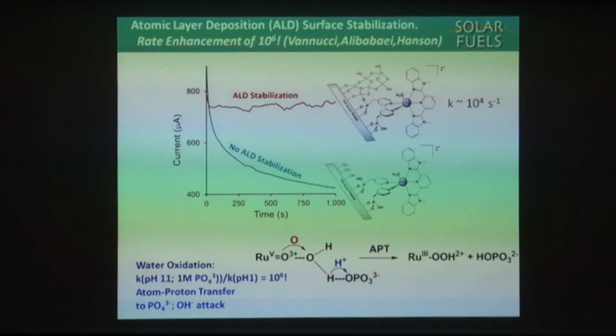With this one, we first bound it and then did ALD, atomic layer deposition, of a layer of titania or alumina, and then these phosphonates become part of a matrix, a mat across the surface, and they're stabilized. And here you can see for an extended period, water oxidation, and it goes on and on. There's something else that's notable here. The rate constant you derive from these kind of data is about 10 to the 4th. There's a rate enhancement here of 10 to the 6th compared to acid solution because of these atom-proton transfer reactions. Under those conditions, that's 10 times faster than photosystem 2. Very simple complex. Control the conditions, control the reactivity.